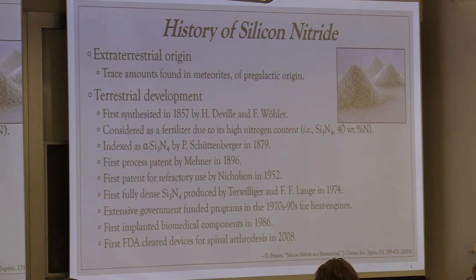Its crystal structure was indexed first in 1879 as alpha silicon nitride, and the first process patents for carbothermal reduction of silicon nitride were granted in Germany in 1896. Its first application as a refractory occurred quite a bit later, over 50 years later, in 1952 here in the United States. But it really took off when Lange and co-workers learned how to take this material and densify it by adding various sintering additives, and that occurred in the mid-70s.